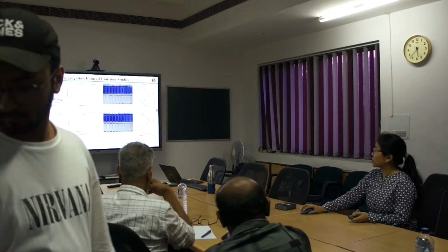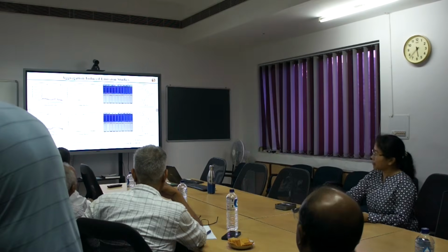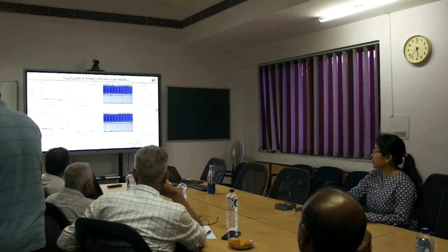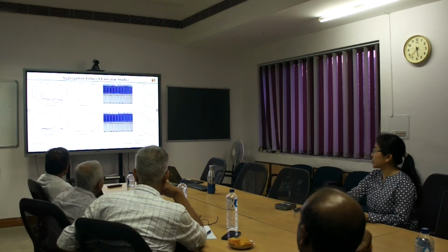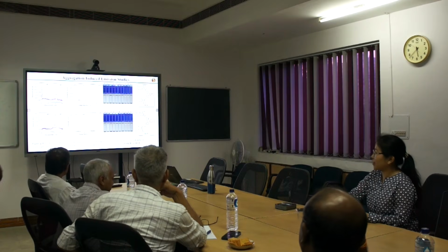In designing this molecule, we expected the molecules to show aggregation-induced emission because of the slight twisting possible because of the dangling phenyl groups. So we maintained the same concentration for the compound and varied the fraction of water in the THF-water mixture. For the QV series, on increasing the water fraction, the emission intensity increased to a maximum at 80% water fraction.